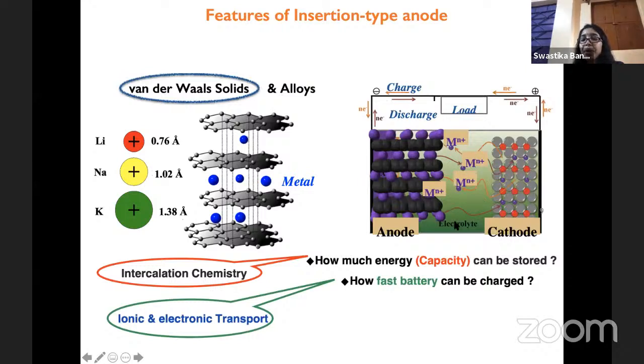So you have two phenomena. One is the thermodynamics, that is the storing of the ions. Another is the dynamics, so it's how fast it can be extracted or inserted into the electrode materials. So with these criteria, if we really want to store the ions into the system, it should have a significant binding energy. But if it is too high, then we cannot extract it at low voltage. So for the anode, when we design the insertion type anode, we need to optimize the binding force of the materials, the elements we are going to store in between the layers.